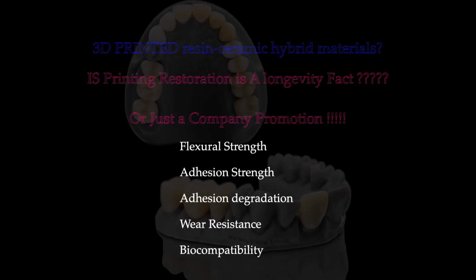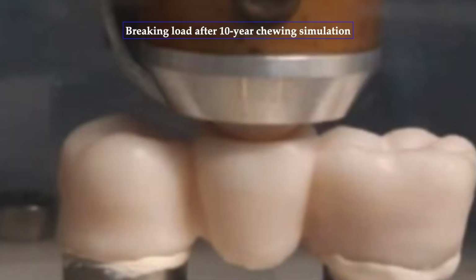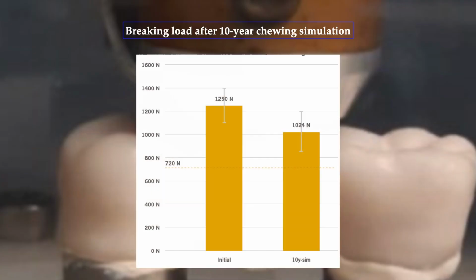So we will talk about some points: flexure strength, adhesion degradation, wear resistance, and biocompatibility, trying to discuss with you if it is a permanent restoration or not. Flexure strength, for some material in the market: the company made research on breaking load after 10 years of chewing simulation, and we can see the result. There is a drop in flexural strength from 1250 to 1024 after 10 years of chewing simulation. It's not a big drop, and this drop is still far away from the shearing force, which is 720 Newton. So it's durable enough to last in our patient's mouth for more than 10 years.